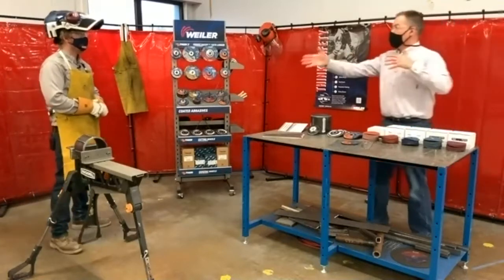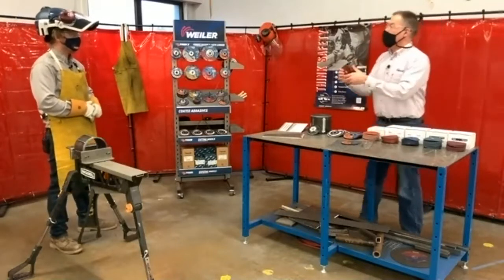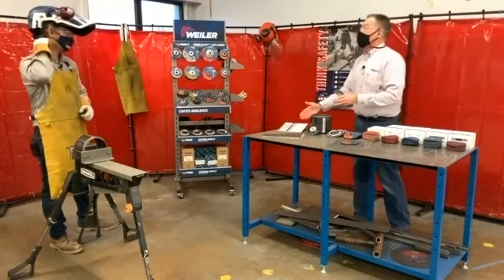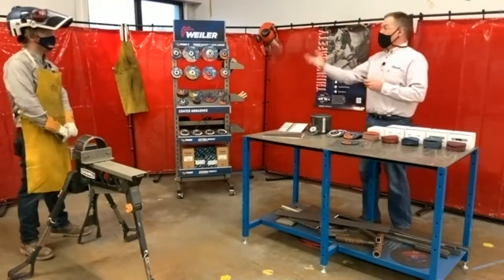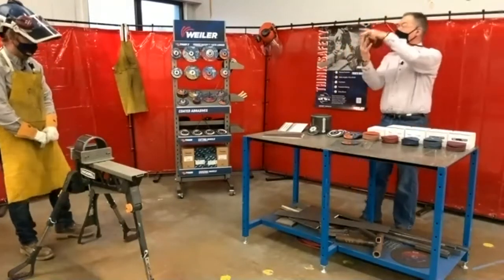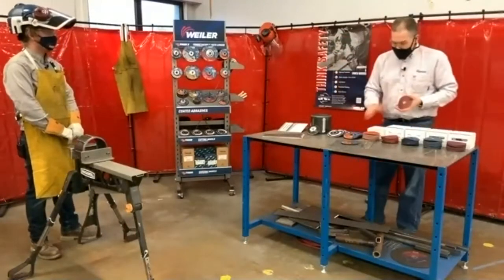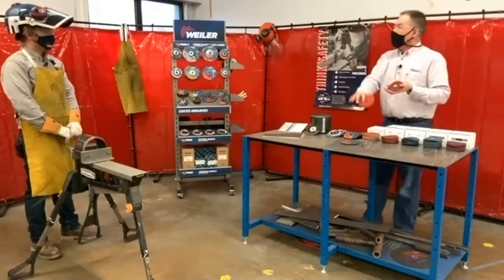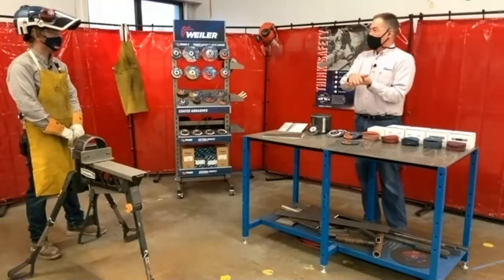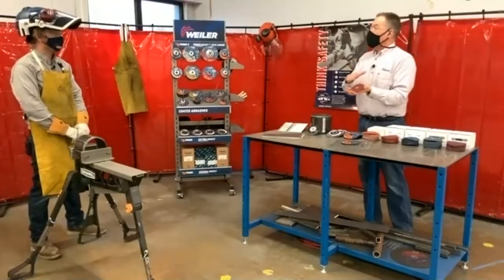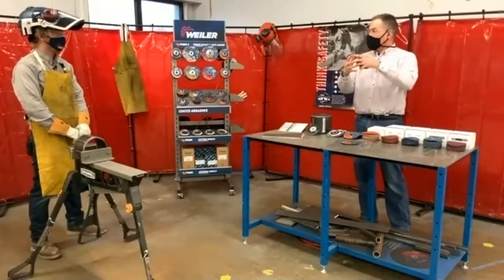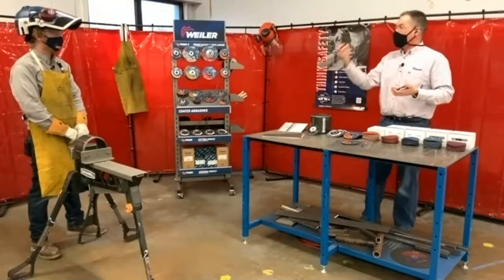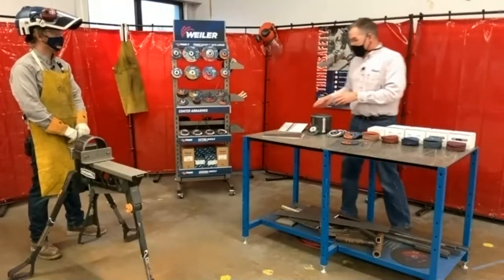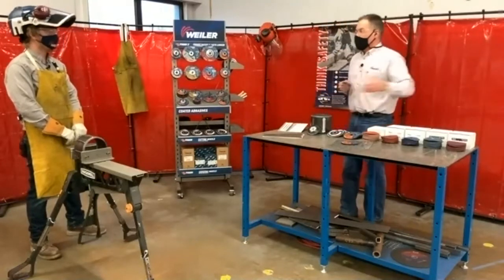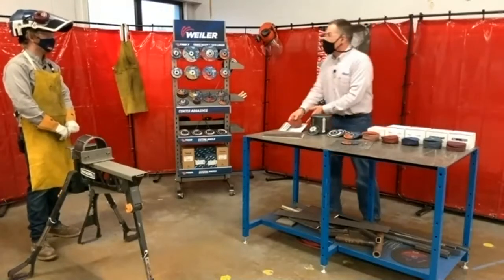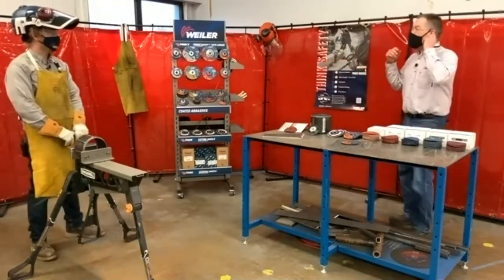Absolutely. And in the interest of time, to talk through just the last rep, we certainly want to talk about aluminum oxide grains and the benefits, particularly in softer materials like aluminum. But one of the biggest challenges with working with those materials is loading, right? That material will want to stick to the sides of the grains and build up. Where we talked about a top coat or a grinding aid to help keep temperatures down, our Tiger aluminum resin fiber disc has a different non-loading formulation that's designed to really prevent that material from even sticking, and allow it to clear as the disc is rotating, to provide that same level of finish that you'd get with a conventional resin fiber disc on a steel part, on an aluminum part, on a copper, brass, bronze, non-ferrous material, or soft aluminum.